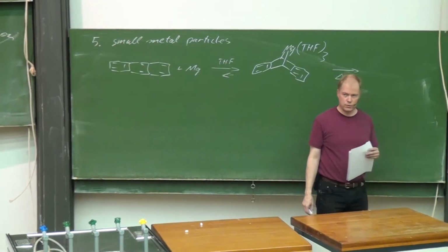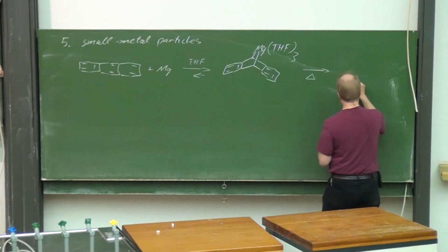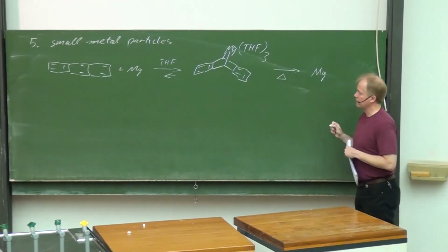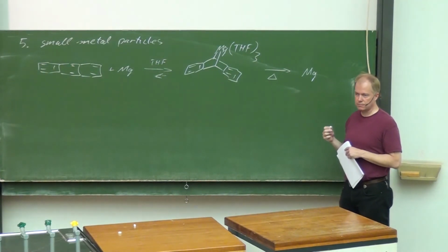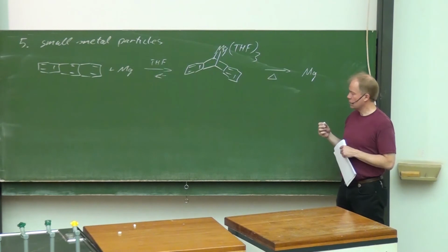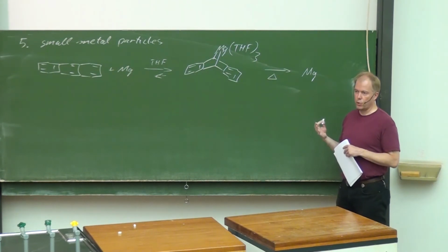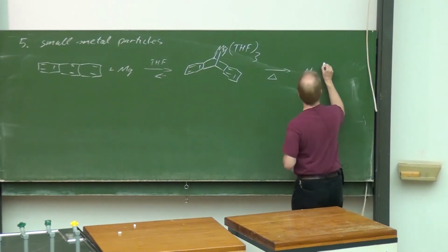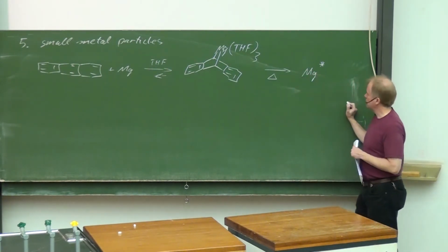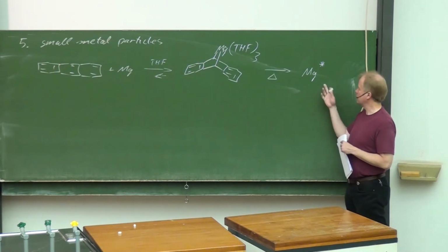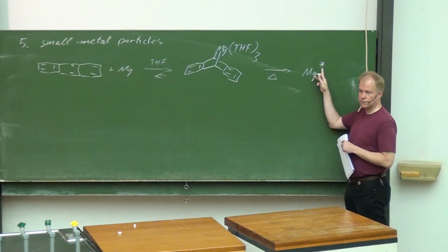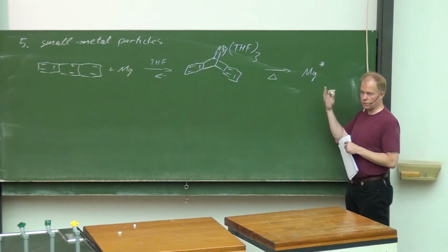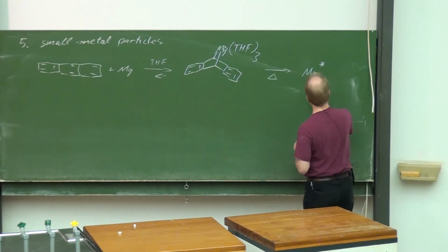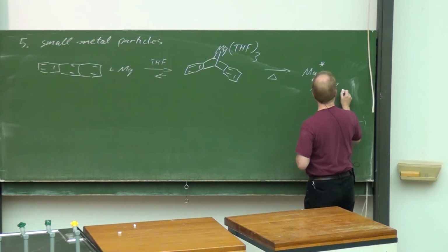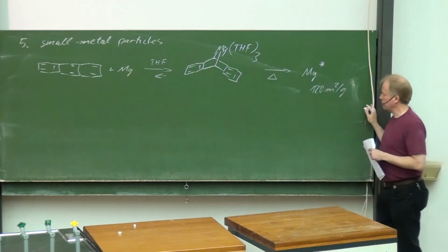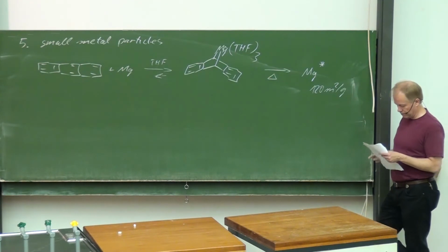Then magnesium is formed, and it's a magnesium with a high surface, a highly activated magnesium. The bigger the surface, the more active, the more reactive it is. And this highly activated magnesium or highly activated metals are very often marked with such a star. That is the mark for high activation. It has a surface of about 120 square meters per gram.